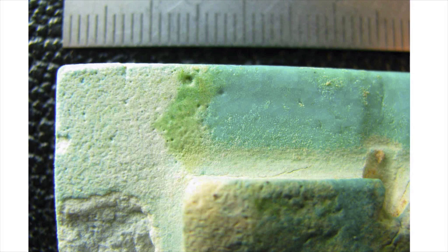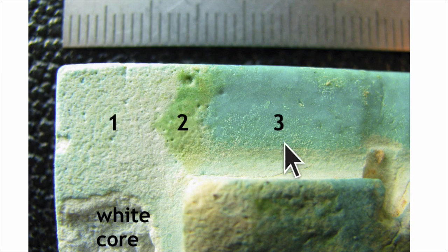Then we looked at the backside, and we found something very strange. If we get close up, we have here the white core. Then we had a first glazing. This is an efflorescent glazing. Then we had the first paint and the second paint. 3 layers. 1, 2, 3.